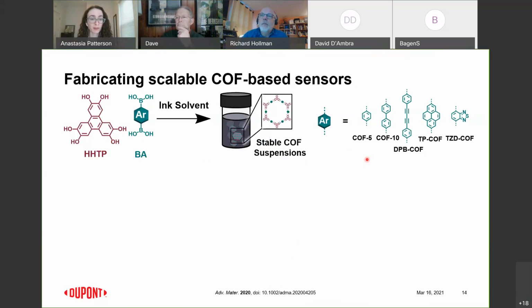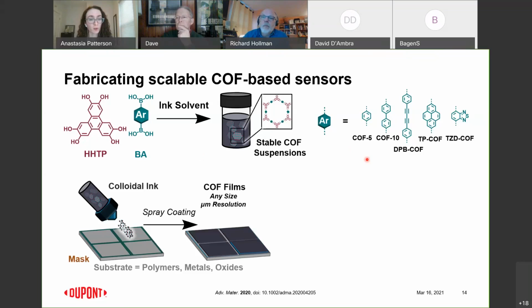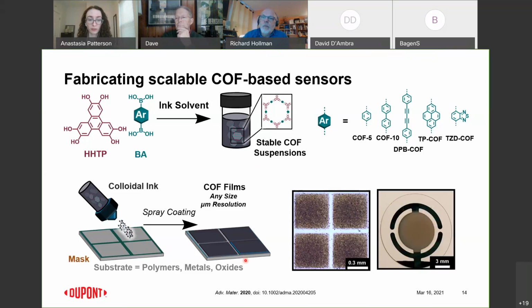Now, how we actually make these devices is through spray coating. Because we can make this stable suspension, we can load up a spray coater with this colloidal ink and coat basically any substrate of interest. We can use masking to block off certain areas if we'd like to prevent those from being coated. Here's a microscope image of some masked areas showing where the colloidal ink is not being sprayed. And then here's our quartz crystal microbalance substrate for the actual testing.